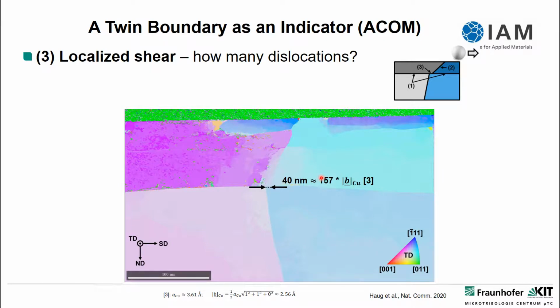And that makes sense, right? It's perceivable that there are 160 dislocations highly confined, moving at the lower dislocation trace line. If it was just one, we would say that doesn't make sense. If it's a million, it also doesn't make sense. But to move 160 dislocations at this very beginning of sliding, that kind of makes sense.